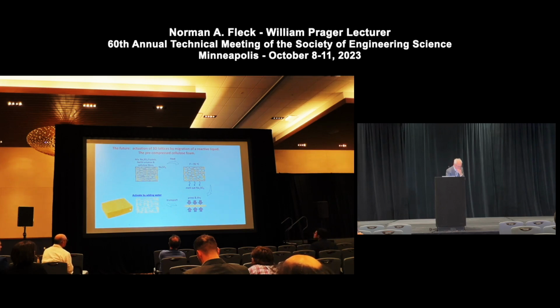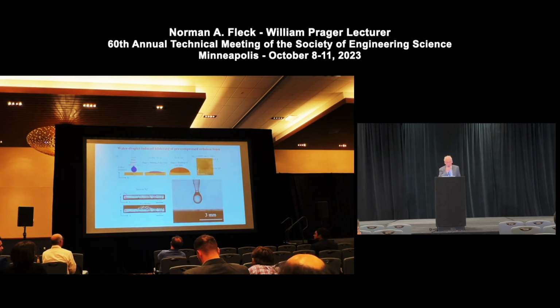And the volumetric actuation is a factor of 10 or more. So the structure reinflates to the cellulose structure of the bathroom sponge. And you can see this experimentally. If you take the compressed cardboard-like structure as shown here, you don't see any voids, any bubbles in it. But if you now add a droplet of water, a side view, see the water absorbs in. Then expansion takes place as the foam inflates due to the presence of moisture, by a factor of 10.